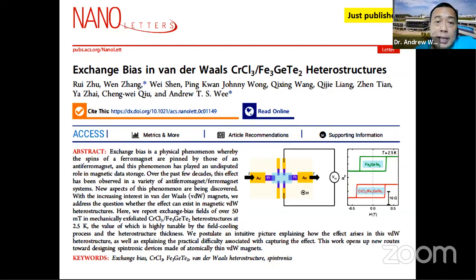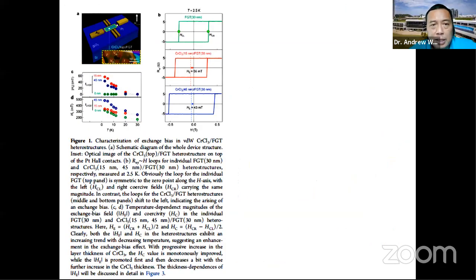And exchange bias is basically the physical phenomenon where the spins of a ferromagnet are pinned by those of an antiferromagnet. And this phenomenon is very important in data storage. All the data storage devices you use depend on this exchange bias. And the interesting thing is, we are not working in the extreme monolayer limit, I must say, but they are very thin films.